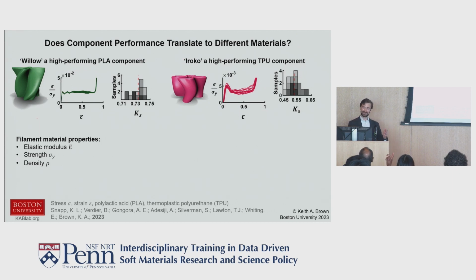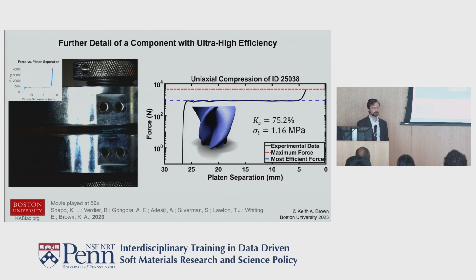Oh, question. Is this completely dissipative? I mean, you're measuring energy absorption, but do you look at what sort of strain you can recover after you unload? We do. As a matter of fact, in the automated process, we test the parts, we lift up the platen, and we come down again to see if they've had any recovery. But generally, a part like this, and this is generally true for anything high efficiency, it's definitely plastic. This is completely crushed.